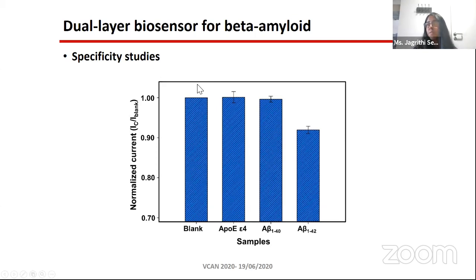So these are the specificity studies that we did. We specifically carried out the studies with ApoE and amyloid beta 40. The reason for doing this is because ApoE is present in 10,000-fold excess in biofluids, especially in blood plasma. And none of the studies that were conducted before have shown a specificity against ApoE or amyloid beta 40, which is really strange because right now the ratio of 40 and 42 is being discussed as a major biomarker, and for detecting the ratio, the individual detection of each of the biomarkers specifically is really important. Therefore we carried out the study with ApoE and amyloid beta 40.